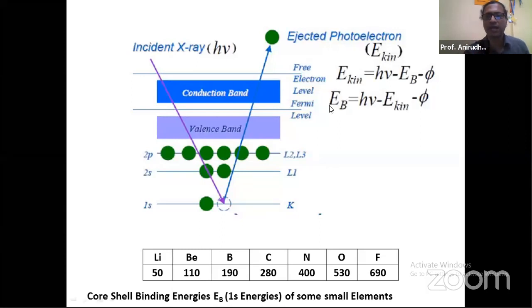So you can calculate this binding energy EB as equal to h nu, because that is the input energy. You know at what frequency it is happening, so you can calculate h nu. If you can measure this E kinetic, the kinetic energy of this ejected electron, using suitable sensors and detectors. So the instrumentation, the sensors part of this equipment, is a very sophisticated one. That is what we should realize at this point, which can precisely measure the kinetic energy of those ejected electrons. Then if you know this calibration constant phi also, which is applicable for your machine, then you can always compute the binding energy associated with that packet of electron which your detector has measured.